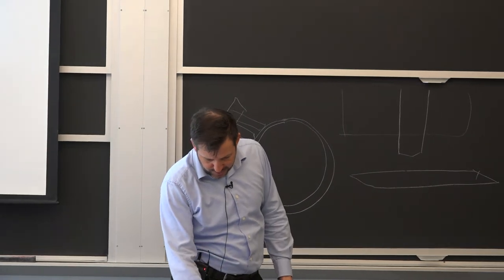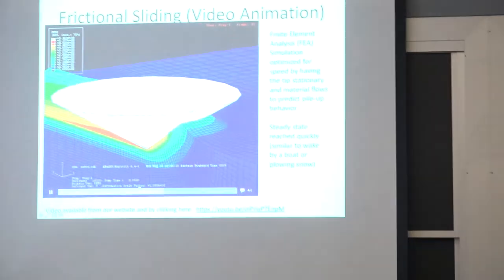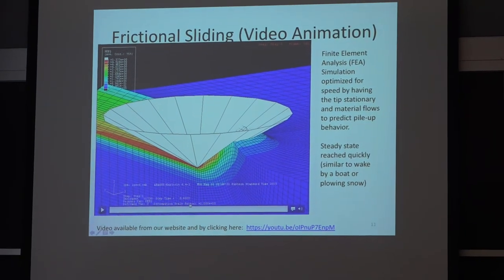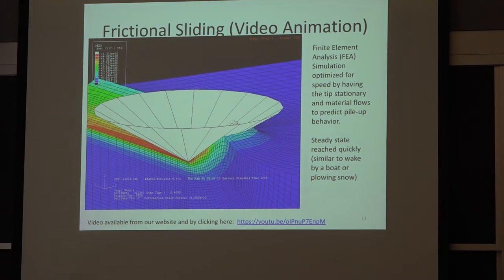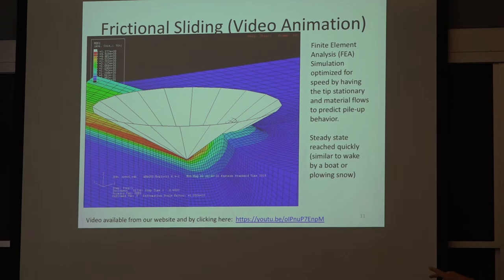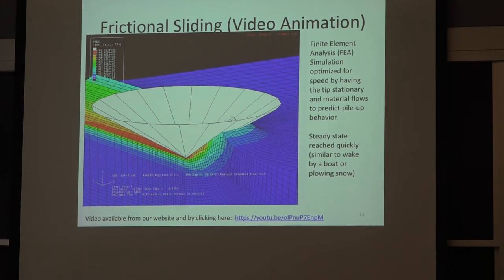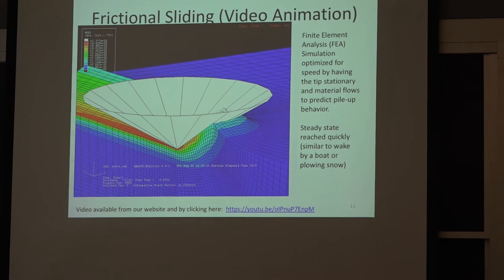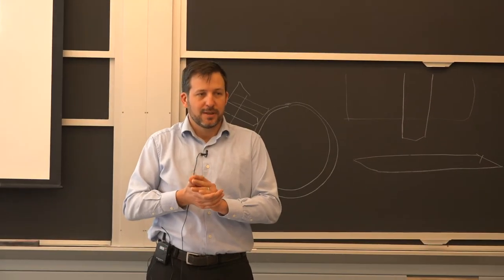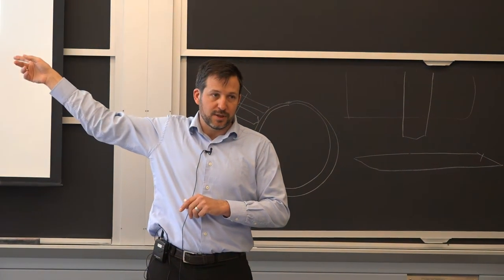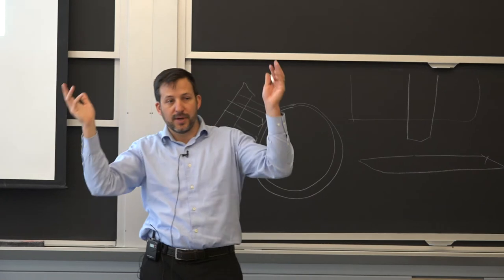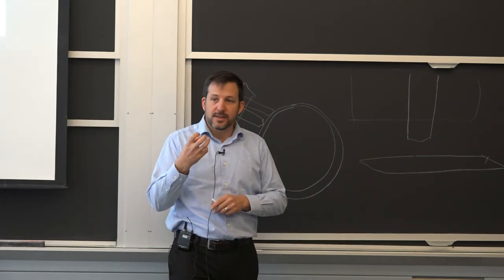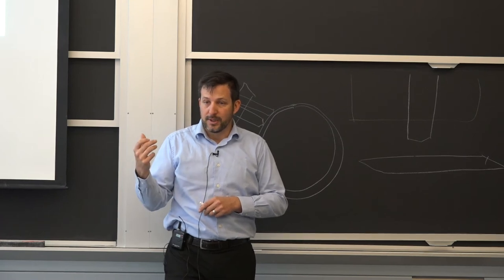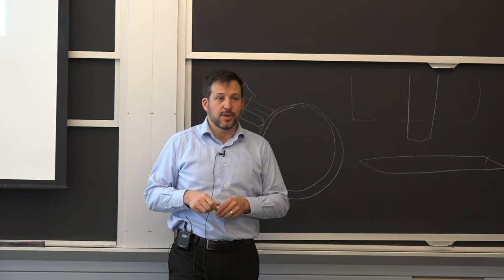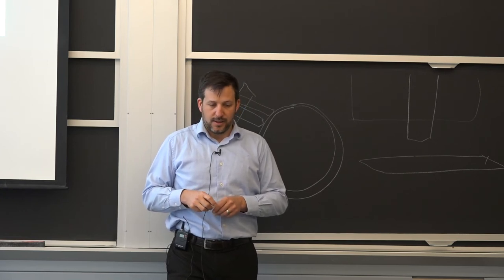Then there's a little story on how it works. Frictional sliding on the surface of the metal gets you into a steady state. So for a certain load applied of the stylus, this is a cone, you form this pileup on the side. And very intuitively, if it's, let's say, wet snow, it's going to harden when you deform it. So it won't make much of a bank on the side of the street. If it's a flurry of snow that's not consolidating, then you make a big snowbank on the side. So there is a strong effect of the work hardening of the metal on that behavior here in frictional sliding. So we're able to differentiate between the initial yield strength and the work hardening behavior.